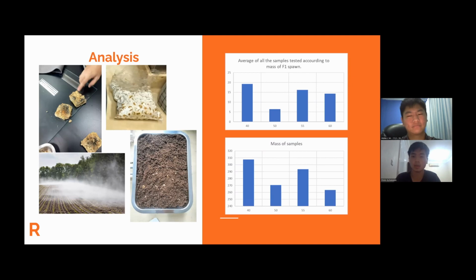Why is this chart going down and up? Well, it's due to several factors. It can be from the fruiting bodies. It can also be from the mushroom itself breaking down the material. And also the primary factor being evaporation. Water can evaporate and cause the mycelium to grow less, or it can cause the substrate to have less mass in general.